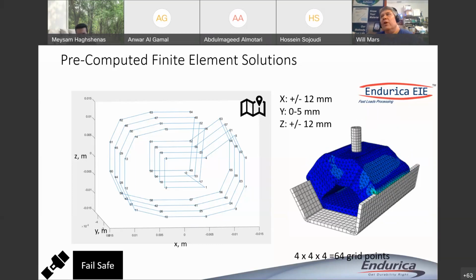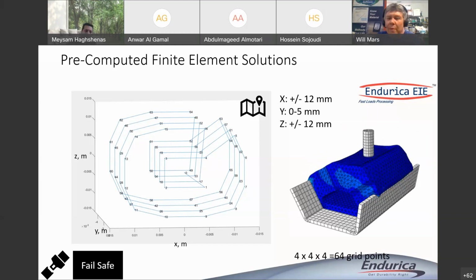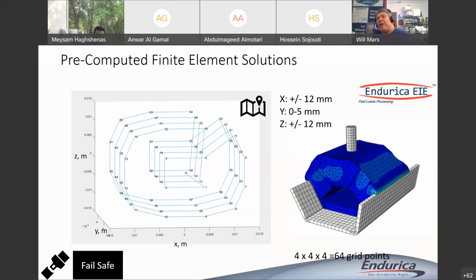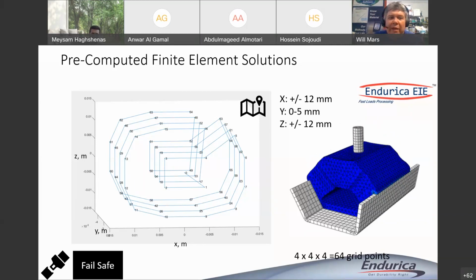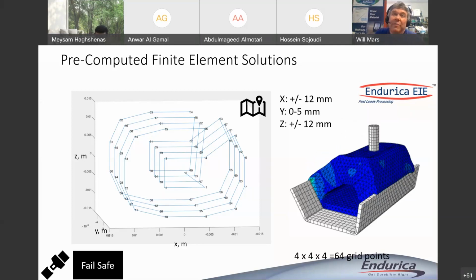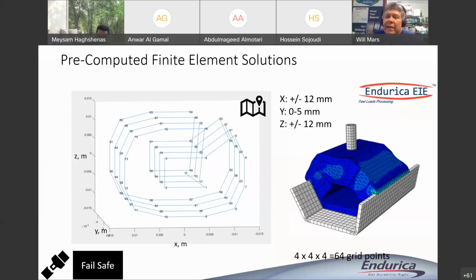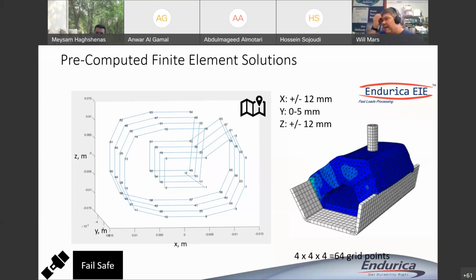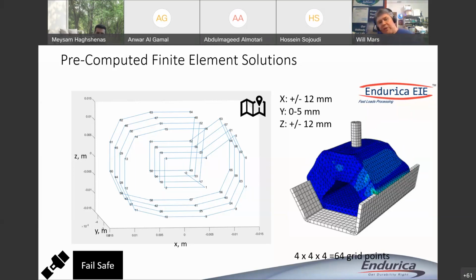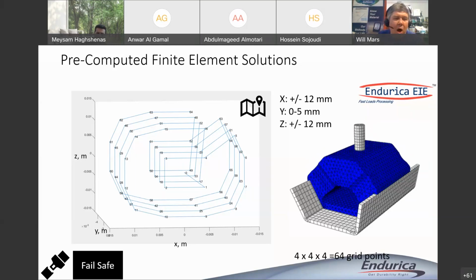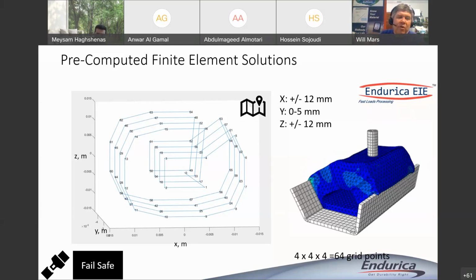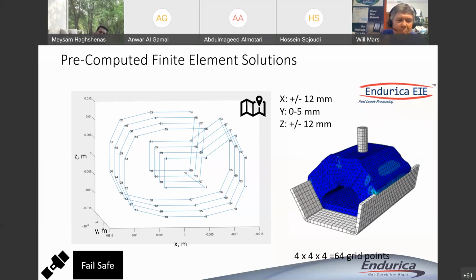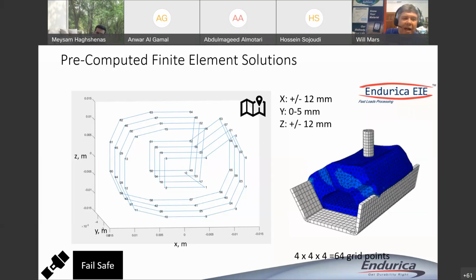For rubber, definitely. So this is one of those tricky questions because at a high level, rubber can be very rate dependent, and I put an asterisk on that because there are also a lot of problems where the rate dependence is not so important. So the question becomes, when is it important to think about rate dependence? And the answer is if the rubber is operating near its glass transition. If you know polymer science, if you plot the stiffness of the rubber as a function of temperature or as a function of rate, all polymeric materials go through what's called a glass transition. At cold temperatures and at very high rates, the material can become much, much stiffer, like 10,000 times stiffer.